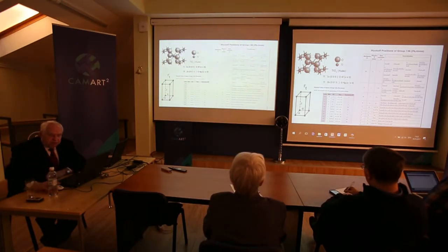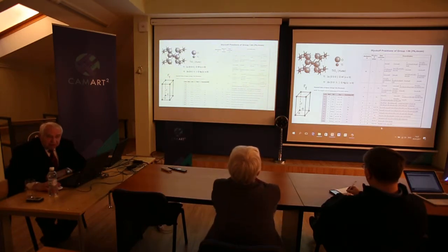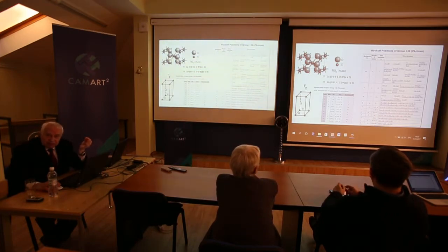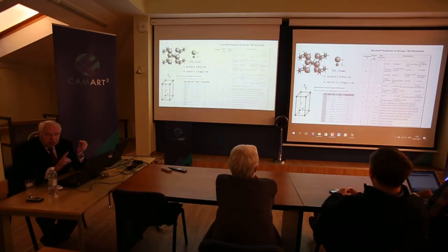What is interesting, and chemists like this, is that non-symmorphic can appear only when you have at least two chemically equivalent atoms in the unit cell. Because what does non-symmorphic mean? That there is some screw axis or glide plane which connects two equivalent atoms. In this case, you see that these oxygens and these oxygens are connected with this screw axis.